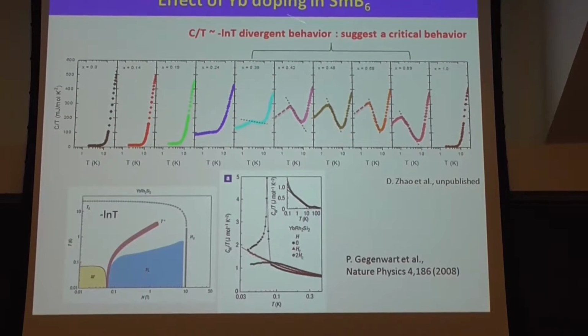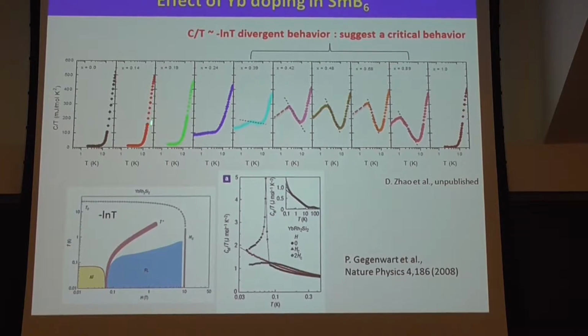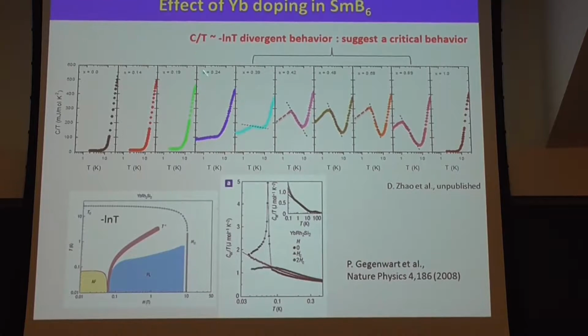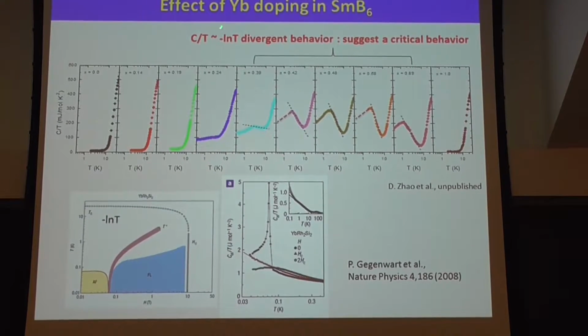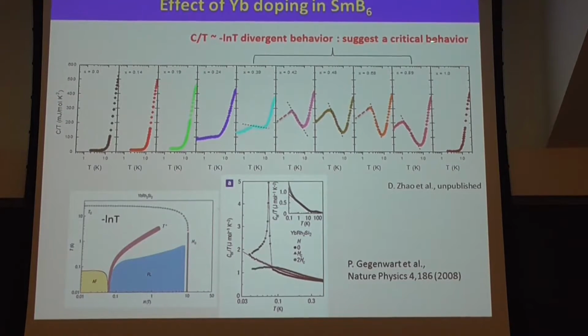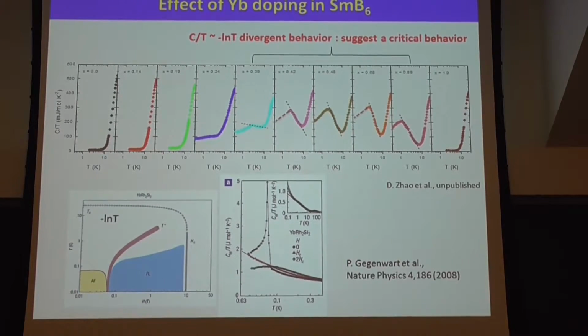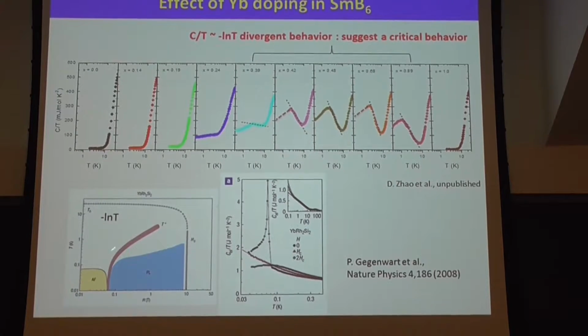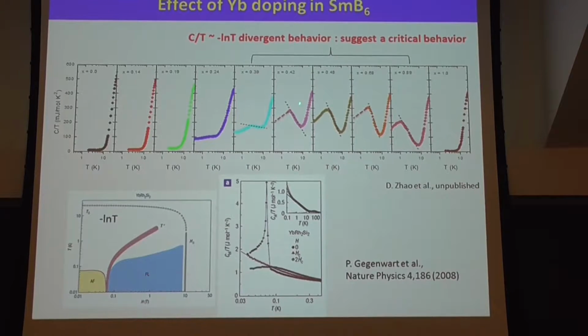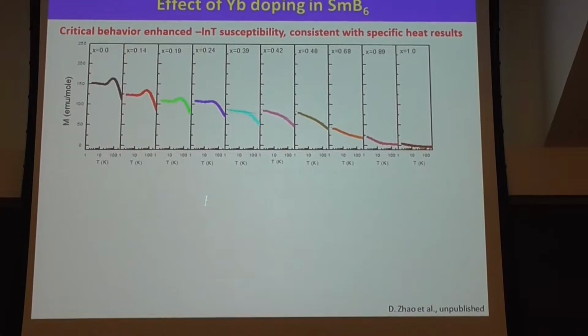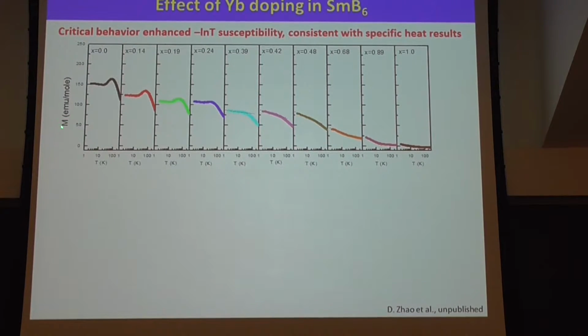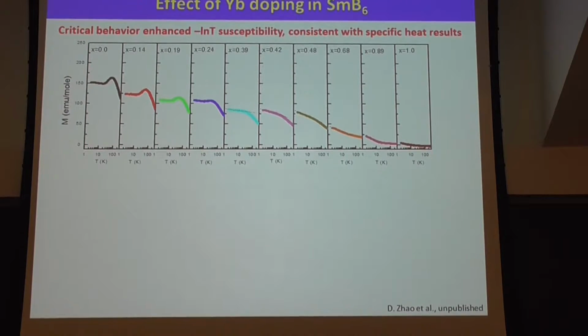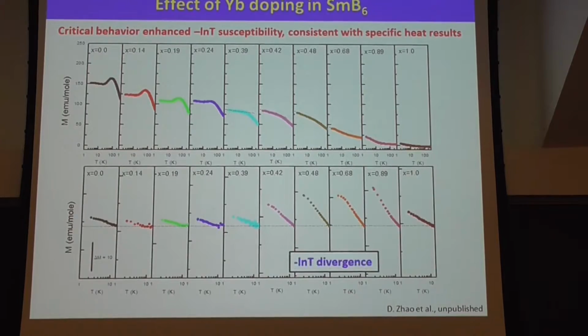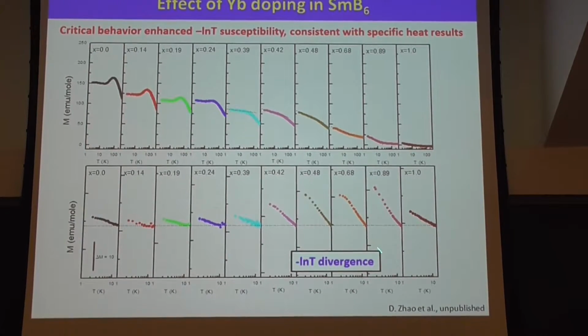Okay, and we also do specific heat measurements on some of the same samples. From the scale, in this region we find some log T behavior. This log T divergence also suggests critical behavior, consistent with what was observed in the NMR measurement in this region. Also in this region, this material shows log T in the specific heat measurement. And we also measured the susceptibility, and the total moment also shows log T behavior. The NMR data, the specific heat measurement, and the susceptibility measurement all show the critical behavior. Here is the magnetic resistance, where you can see this log T divergence.